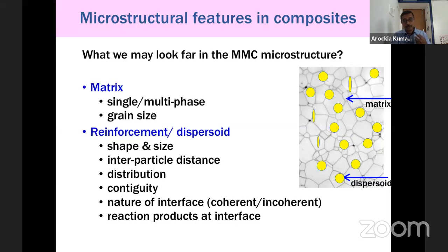So to get a better property, we need to avoid this hard particle interface. And then the nature of the interface, whether it is coherent with the matrix or incoherent with the matrix. Generally, we prefer a coherent interface for better mechanical properties. And then whether any reaction products have been formed at the interface. For example, in an aluminum silicon carbide composite, if the processing temperature is very high, then at the surface aluminum interacts with carbon and aluminum carbide forms, which is deleterious for mechanical property.